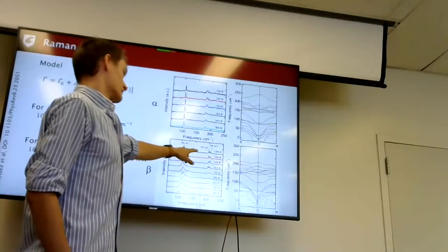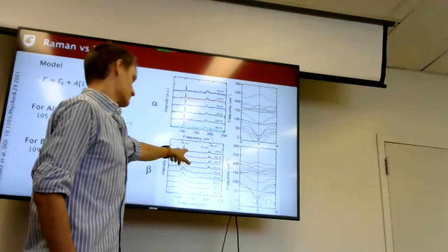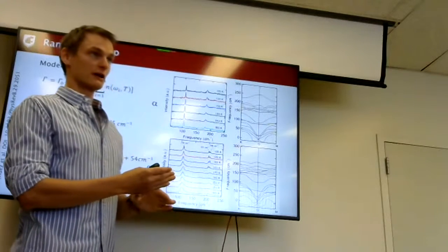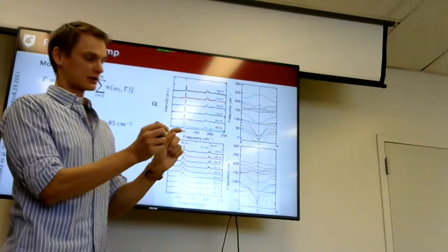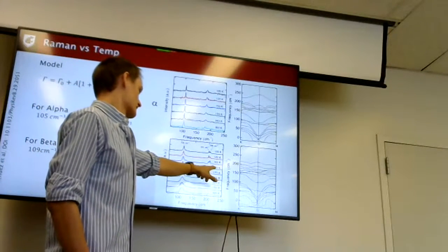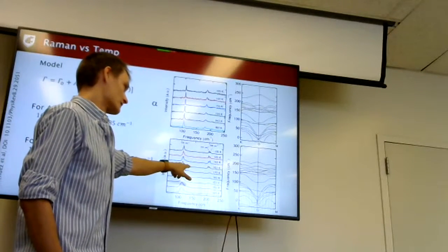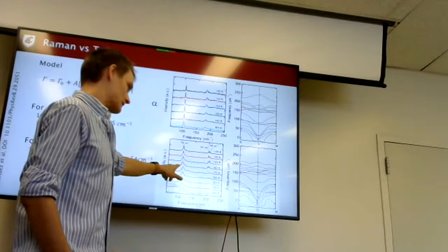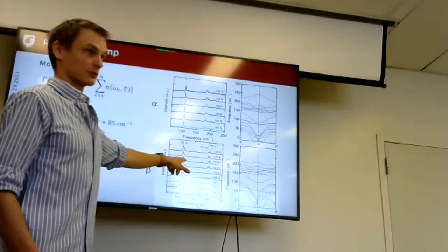The problem with beta is that at very low temperatures, you get 2 peaks, but as you heat it up, these peaks collide with each other, they move closer together, and their full width half maximums increase. And at about 160 K, you get a third peak off on the side that's very broad, and that very broad peak starts to spill into these other 2 and makes them indistinguishable.